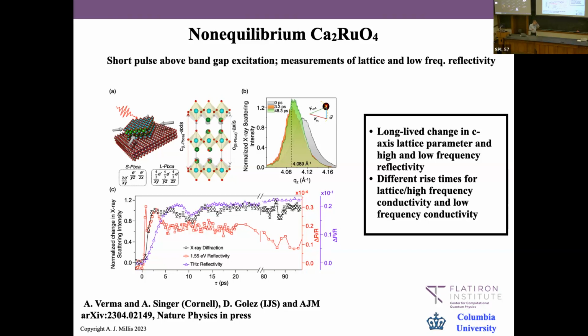So at what time it gets back, they don't know—basically, for technical experimental reasons which I'm not fully on top of, they can't go to more than 100 picoseconds. It does get back to equilibrium on the time of probably nanoseconds, but they don't know at what time. It doesn't stay forever in the non-equilibrium state, but it stays for a remarkably long time.